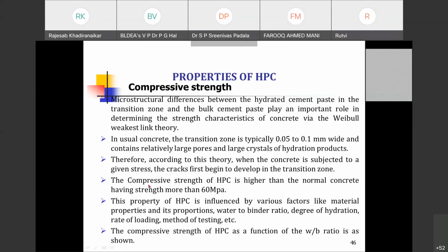So the second property of hardened concrete is compressive strength. As you know, the strength is more in this case, as the microstructural differences between the hydrated cement paste, the transition zone and the bulk cement paste play an important role in determining the strength characteristics of concrete. This is the well developed Weibull weakest link theory. You have studied earlier that the transition zone is the weakest link. So now it has been strengthened, and by virtue of that, you have the increased strength.